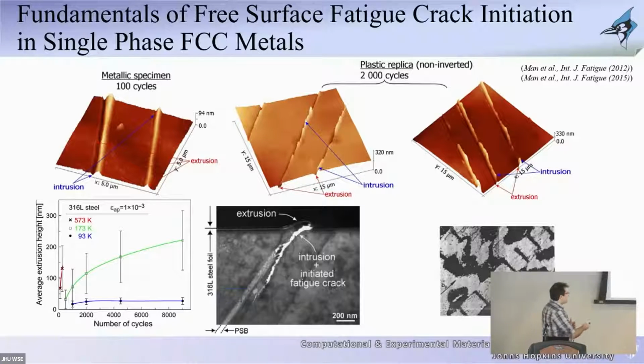Now, the intriguing thing associated with this crack initiation and that extrusion is that if you look at the microstructure, the defect structure that is within this range, which is called a PSB, a persistent slip band that led to that extrusion, it would look actually something like this. So this is a TEM image. This is Hael Mughrabi, the professor that I mentioned, whom I would consider the father of fatigue. He was able to show that what leads to these extrusions is the formation of ladder structures, representative ladder structures, that are composed of dislocations.